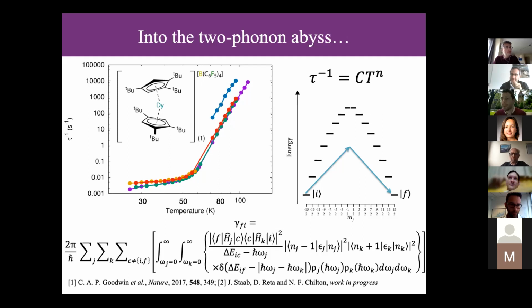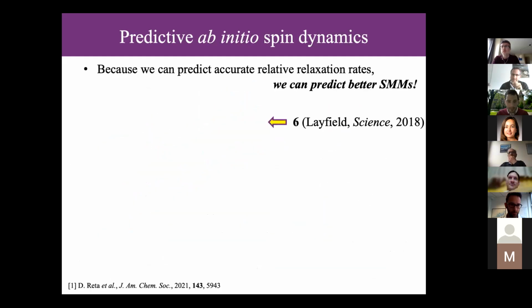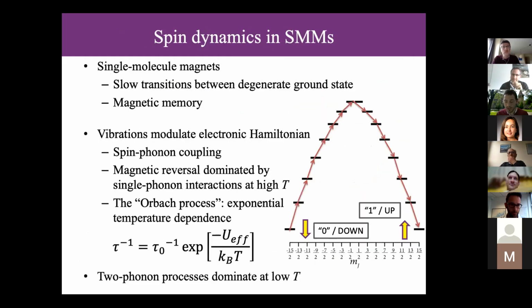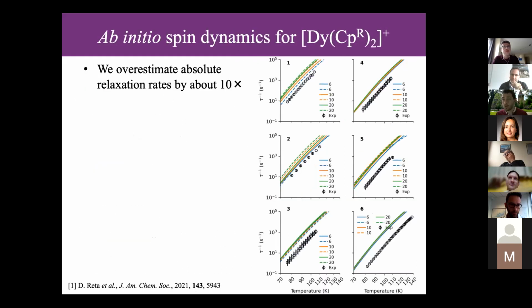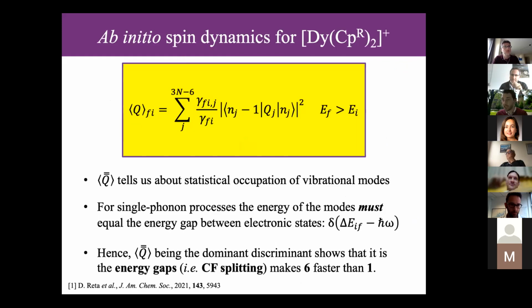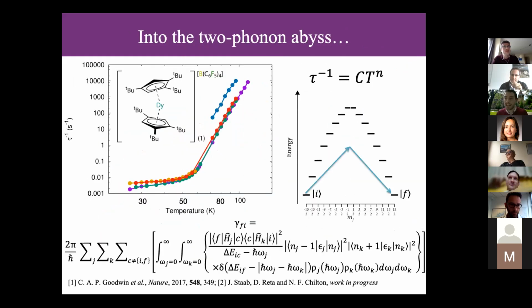Remember, the rate of an Orbach process goes towards slow times exponentially quickly. Like it goes very, very fast, right? Because in a good single molecule magnet, you have gaps that are hundreds and hundreds of wave numbers. In the first dysprosocenium SMM, this is 470 wave numbers. So the occupation of a vibrational mode at 470 wave numbers, go and do the Boltzmann, your statistics are really, really bad as you start going cold. So this shoots down exponentially quickly, right? So you disappear so quickly that whatever's underlying is going to be there. So it's kind of irrelevant to say it's going to be faster.